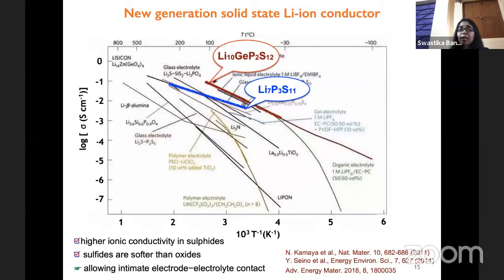So if we look at the literature survey, we find Li10GeP2S12 is one sulfide-based conductor, and Li7P3S11 is also a glass material, also based on the thiophosphate framework. They are very promising in terms of lithium ion conductivity. And if you see the scale for the conduction, these are in the order of 10 or more than 10 millisiemens per centimeter. So these are really competitive with the conventional liquid electrolyte, and surprisingly, we are now crossing the limit, going beyond the liquid. So with solid, we can achieve the conductivity. However, there are several other issues like the stability and other stuff.